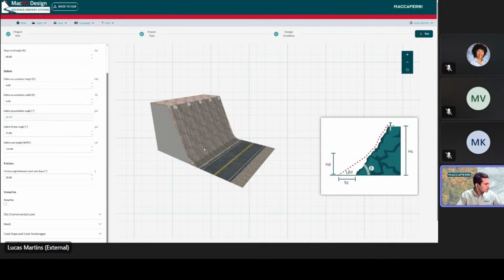and about 80 feet high. We are going to consider a material accumulation of 4 feet by 4 feet. That means that the debris accumulation is going to have those dimensions. I'm going to show a little trick later on how to verify if this is appropriate or not. For the friction angle, the debris friction angle should be entered as about 75% of the residual rock friction angle, and the debris unit weight would be also 75% of the intact rock unit weight. For this, I'm going to leave 125 PCF and 25 degrees.